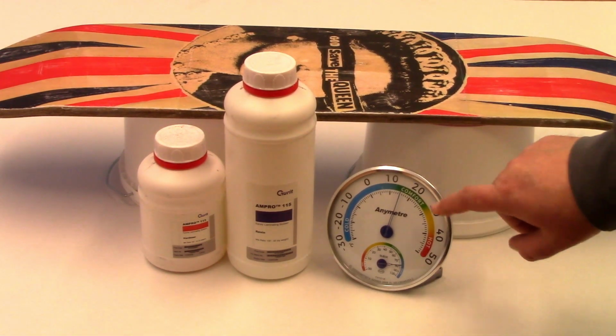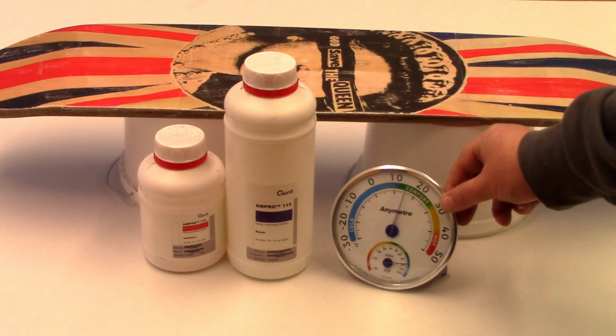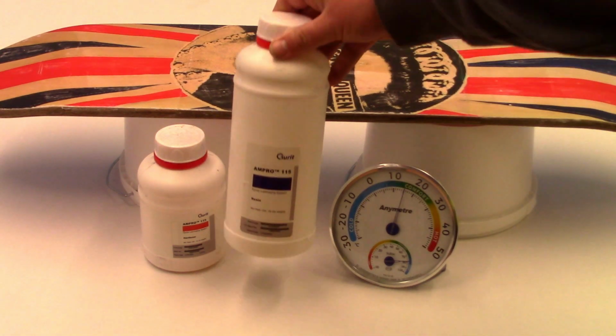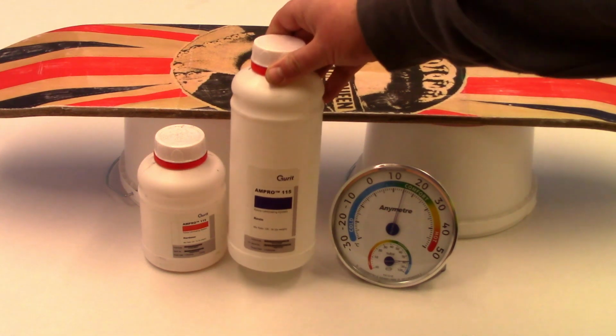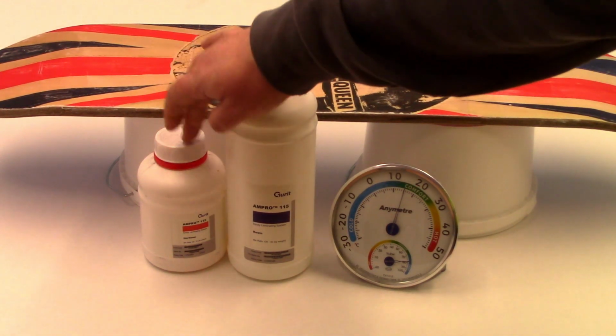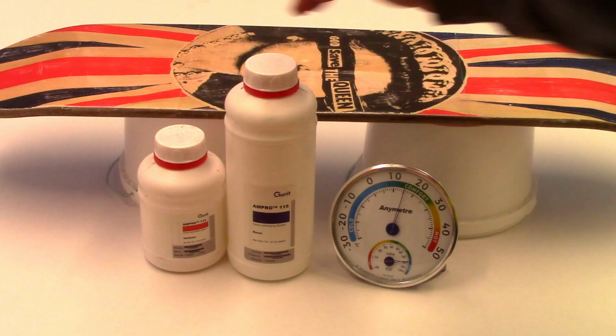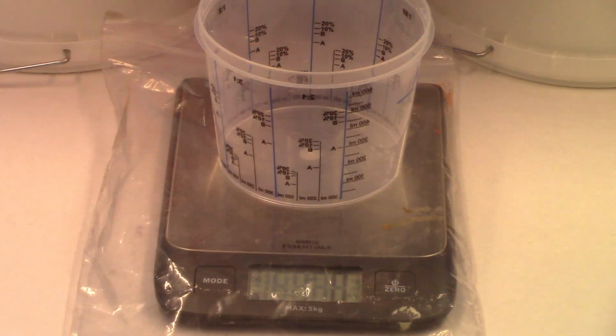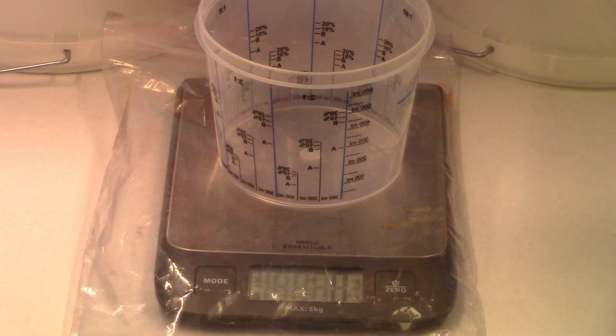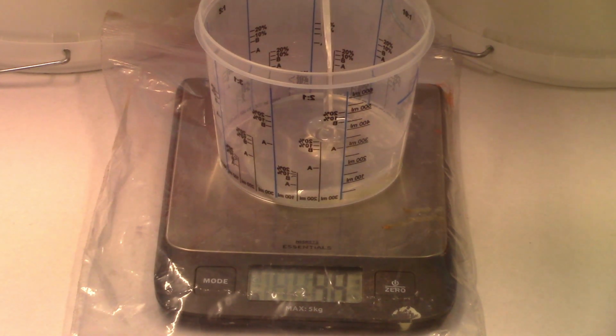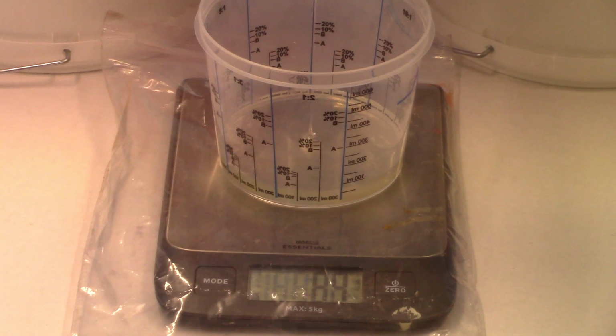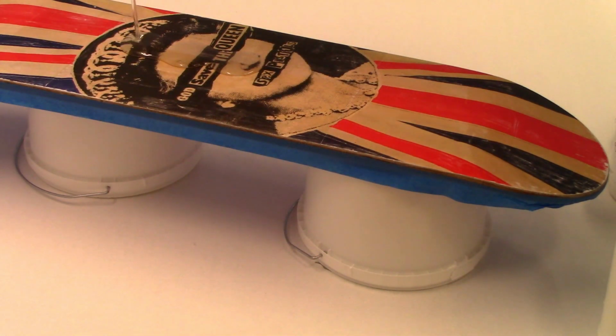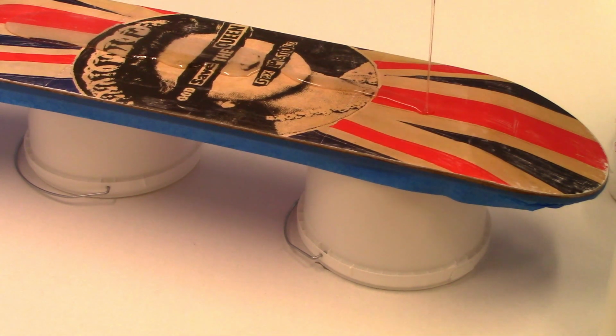The room temperature should be around 15 to 20 degrees C, as well as conditioning the epoxy to the same temperature. Here we're going to use Gurit's Ampro 115 clear epoxy resin. This resin and hardener is measured at the correct ratio by weight using digital scales. Once mixed, the epoxy is poured onto the board, and using a clean foam brush we spread the epoxy out evenly, adding more epoxy if required.